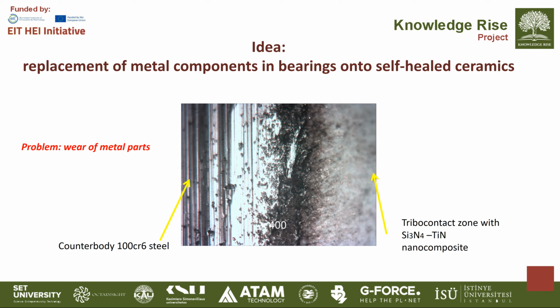Replacing steel with self-healing ceramic allows bearings to operate at high temperatures, with reduced lubrication, and in corrosive or vacuum environments, conditions where metals typically fail. Moreover, the lower wear rate and self-repair ability significantly extend service life and reliability. The wear of metallic bearing components remains a key limitation to achieving long-term durability and efficiency. The transition to self-healing ceramic nanocomposites provides a transformative solution, combining superior tribological performance with autonomous surface restoration. This approach paves the way for the next generation of smart, maintenance-free bearing systems in aerospace, automotive, and industrial applications.